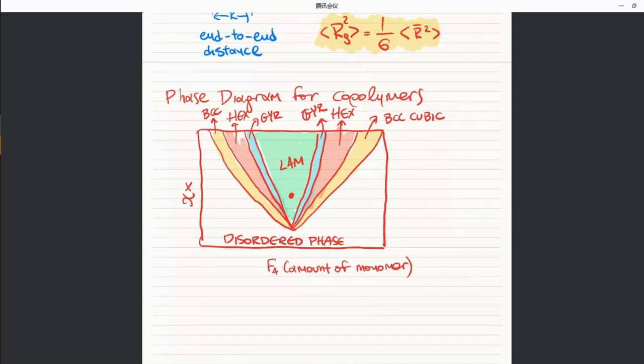What happens if I increase the temperature? One more answer. Okay. Indeed, we will move towards the disordered phase. Okay. And why is that? Because we already said that the Flory-Huggins interaction parameter equals A plus B over T. A and B are constants that are positive. So chi is proportional to 1 over the temperature.